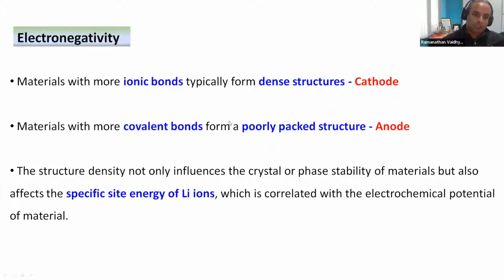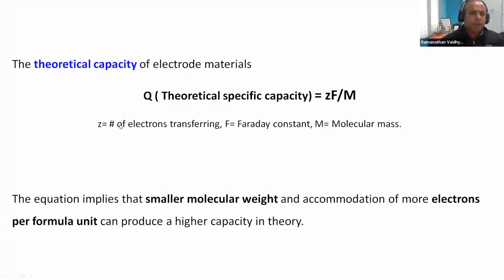Now, if you look at a general principle for making an anode, you find that if a lot of covalent bonds are present in your structure, which is decided by the electronegativity of the atoms forming the material, you get a poorly packed structure with a lot of covalent bonds, and they are more suited for an anode. This is why in a lithium-ion battery, graphite is used as an anode. Whereas for a cathode, you need materials with strong ionic bonds, which form dense structures. And essentially, if you have them very crystalline, then you're going to have a high degree of site specificity, which is very important for the movement of ions in and out of the material and to be able to find the exact sites of interaction.